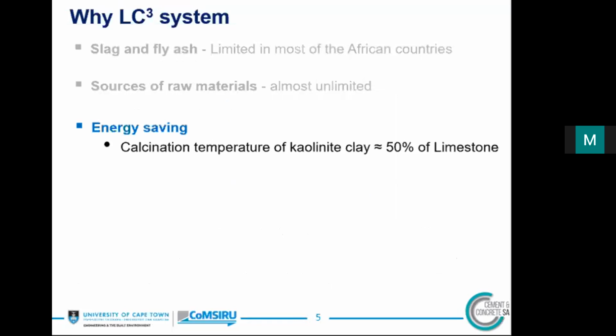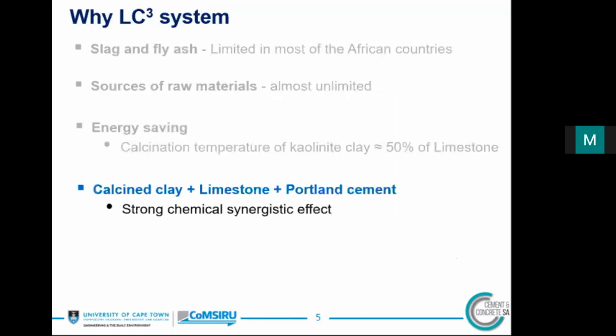Number 3 is about energy saving. Now, in this system, energy saving occurs because the calcination temperature of clays is lower than that of clinker by almost 50%, and they're also easy to grind. There's also a strong chemical synergistic effect when all these 3 materials are combined together, but they should be in the right proportions and the right sulfate and alkali content. So in general, the increased compressive strength and the penetration resistance of this system is linked to the porosity refinement produced by the pozzolanic reaction and formation of carboaluminate phases.